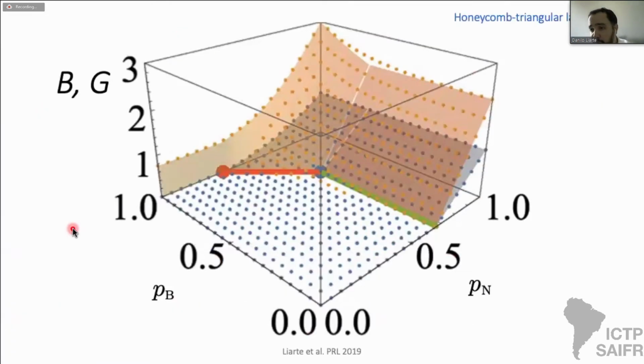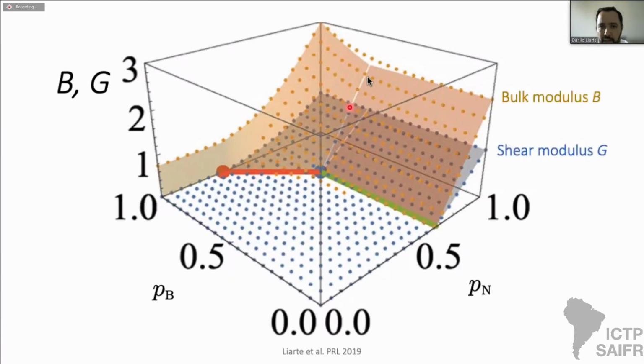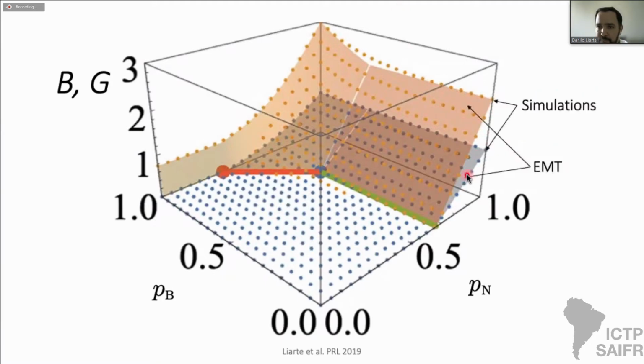Now let's take a look at what we obtain for the behavior of the moduli near this rigidity transition as a function of PB and PN. There's a lot going on here, so let me walk you through this. There's a floppy phase in this white region here, and a rigid phase above the red and green lines. Yellow represents the bulk modulus and blue represents the shear modulus. Dots represent simulation data and the surfaces represent our effective medium theory results. And at this point, it's worth noting how good the agreement between these two approaches is.